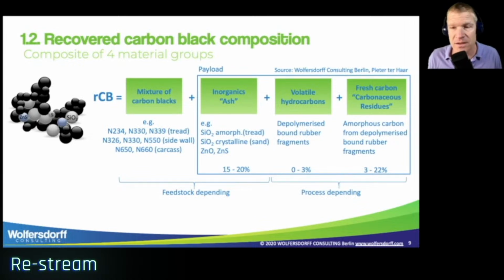So here we can create value with a very low PAH content. For that, we need a low total content of volatile hydrocarbons. So I'm saying 0 to 3%. 3% is the maximum we can bear, bearing in mind that we might have 1%, 1.5% of moisture. The rest, if it is aliphatic hydrocarbons, this is good, but they shouldn't be aromatic, and we need to analyze that.